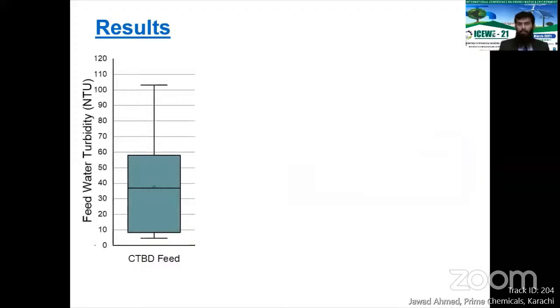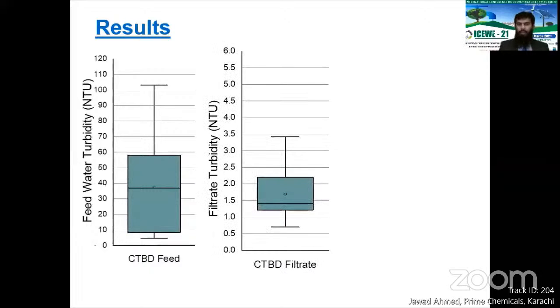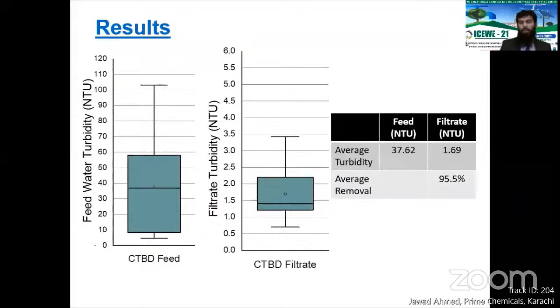Now the results in the form of turbidity. We can see the feed water turbidity on the left. For the current scenario, it varied from less than 10 NTU to over 100 NTU, with a mean value around 40 NTU. In the filtrate, we had a median value of around 1.6 or 1.7 NTU, and we can see a drastic reduction with all data sets lying below 3.5 NTU and primarily below 2 NTU. So we can see an average removal of over 95% in terms of turbidity.